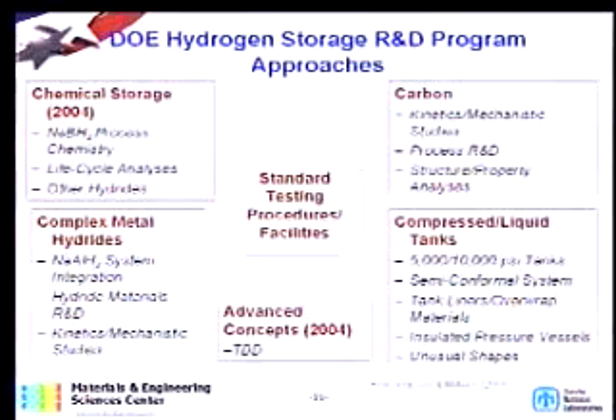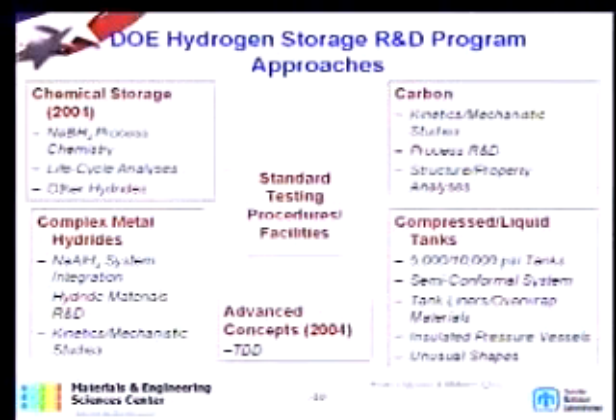The second mature one is the hydrides. And most recently, the complex metal hydride, like sodium aluminum hydride, promised to provide 4 to 5 weight percent hydrogen at moderate pressure and near room temperature, about 100 degrees. However, there's another problem with that. Even though the 4% is attractive, it's not meeting the DOE's requirements. And then there's, of course, the carbon nanotubes, which has been a very controversial issue. The previous speaker talked about there still being a debate: does it really work or not? And I will talk a little bit more if I have time.